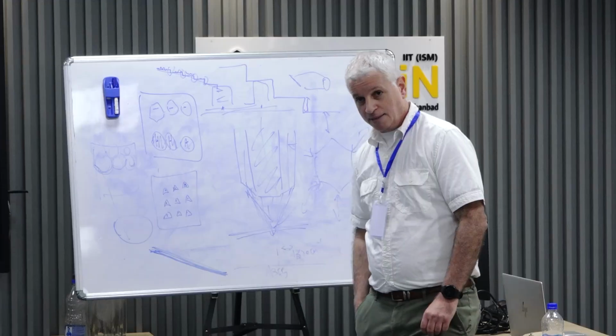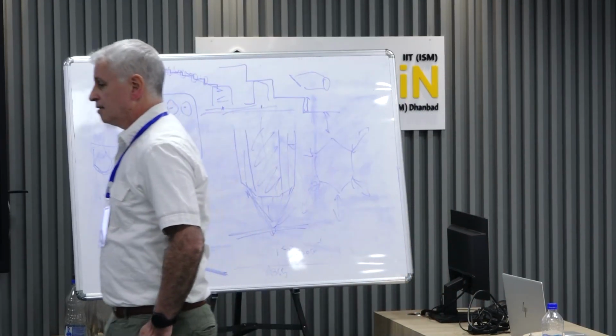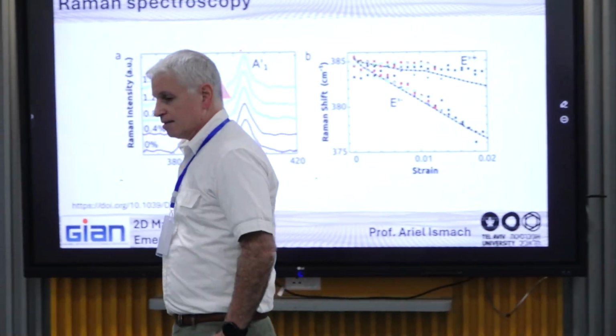And that is one of the reasons that, in contrast to graphitic materials and TMDs, it is very hard to characterize single layer hBN. Because in order to do so, you need to go to other methodologies that are time consuming. There is nothing as fast and efficient as Raman. And that is detrimental for the growth process, for the growth development. And we see that the growth of hBN is less advanced, let's say, than the film.